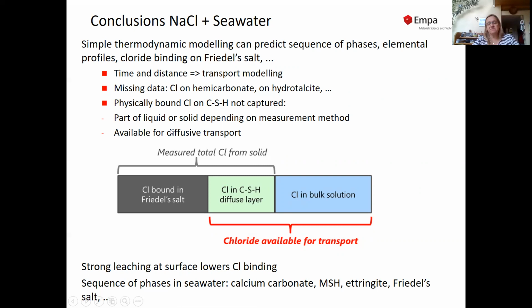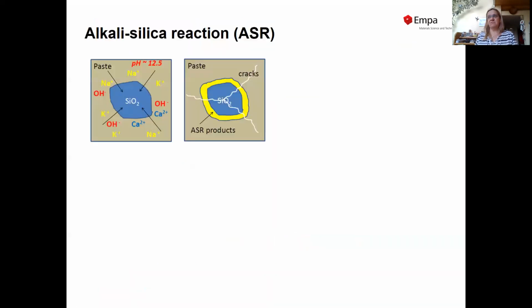Maybe just as a word of caution, if we do thermodynamic modeling, we generally predict only the chloride bound in Friedel's salt. We do not predict the chloride present in CSH, mainly because we don't have thermodynamic models for that yet. While when we do measurements, for instance, elemental mapping, we normally include the chloride in CSH also in the data. We see it as part of the solid because we filtrate, or we take away, the aqueous solution. If we look at transport, then the chloride in the CSH is rather part of the chloride that can be easily transported, and then we have to look a little bit differently at things.